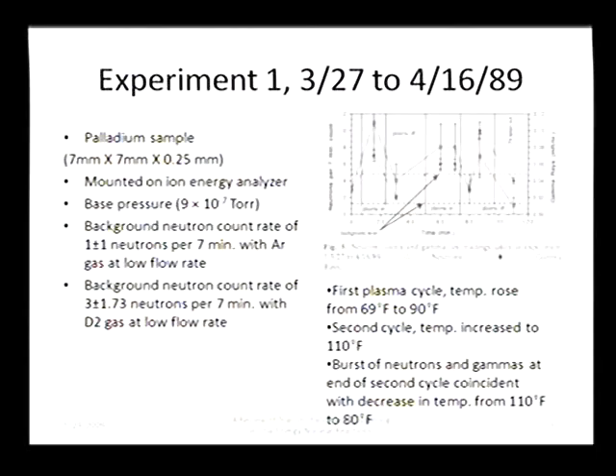And the experiment was done where we cycled it with plasma, no plasma, plasma, no plasma. And what we saw was that count rates went up with the plasma, and they went down, but it didn't go coincidentally with the shutoff of the plasma. It decayed. And then basically, when we turned the plasma on, we had the same sort of behavior. Count rates went up above background, then went down when the plasma was turned off. And we cycled it several times. And one of the more interesting things is that when we saw the largest burst of neutrons and gammas at the end of the second cycle, they were coincident with a decrease in temperature going from 110 Fahrenheit to 80 Fahrenheit.